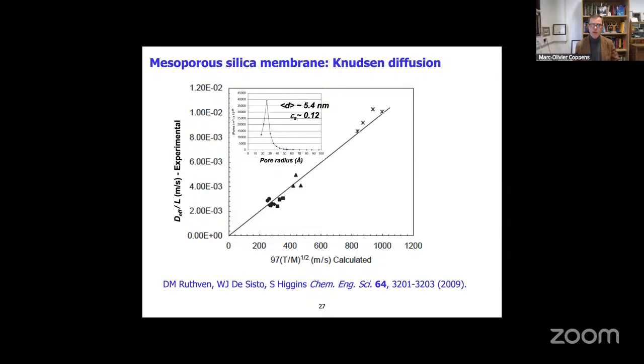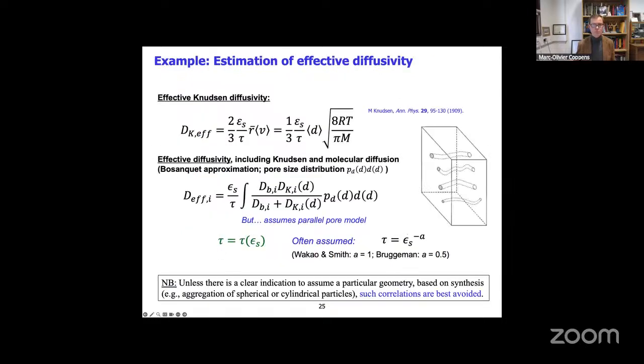So it needs to be a well-made material with a clear, here, unimodal distribution of its pores. So the pores are neatly around 5.4 nanometers. And then indeed, you have a well-characterized material and you can use these formulas for the Knudsen diffusivity, like the ones I showed here, right?